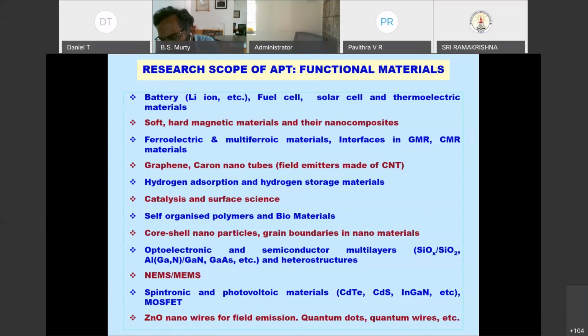Wherever you have a very small sample, let's say I have a nanoparticle of about 5 nanometers, what we typically do is put that nanoparticle on the tip of a sample, glue it, and then sharpen that nanoparticle in such a way that it is a very sharp tip, and then put it into the atom probe. So this way we can see any type of materials. A large number of groups inside the country, and even some from outside, use it. For example, one of the steels that I showed you was from a gentleman coming from South Africa. He wanted to use our atom probe. There are people from outside the country also coming and using it.